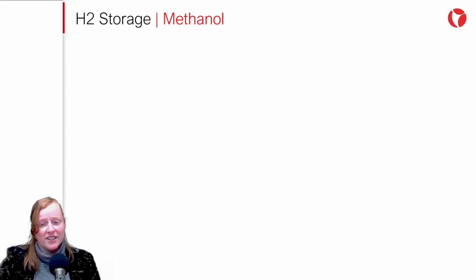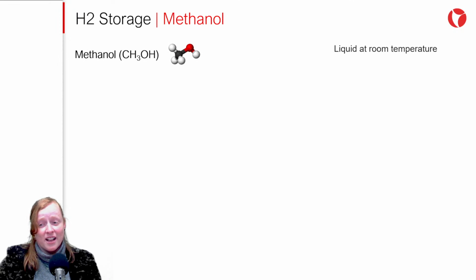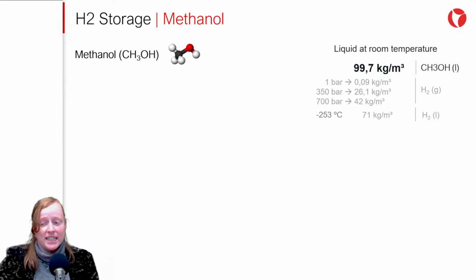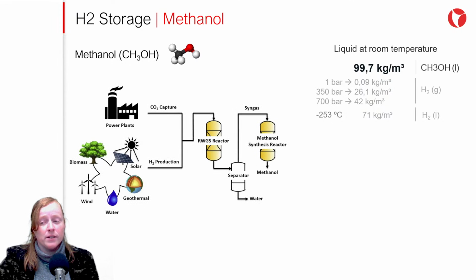Another hydrogen carrier of great interest is methanol. It's an alcohol, thereby containing carbon, that remains liquid at room temperature. Its volumetric density is greater than that of liquid hydrogen, but lower than ammonia. The synthesis of methanol from green hydrogen requires the contribution of a stream of previously captured CO2. Two processes are used to synthesize methanol: direct and indirect chemical conversion of CO2. In the first, CO2 is directly converted to methanol, while in the second, CO2 is first converted to syngas in a reverse displacement reactor, where it's then used as a feedstock in the methanol reactor. The efficiency in the methanol synthesis process can range from between 40 to 70%.